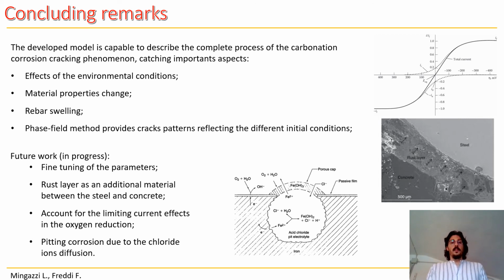We're still working on this topic. However, we have to fine-tune the parameters to account for a wider variety of environmental scenarios, such as wet and dry cycles, etc. We'd like to add a rust layer as an additional material between the steel and the concrete in order to account for its mechanical effects on the crack pattern. We'd like to add a limiting current parameter for the corrosion process. And lastly, we'd like to extend our model to describe the pitting corrosion due to the chloride ion diffusion inside the concrete.